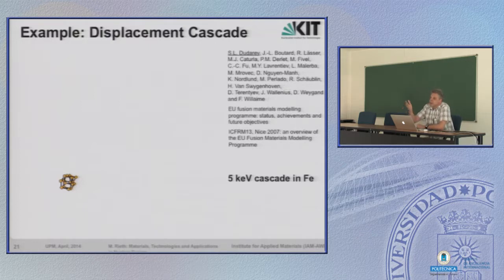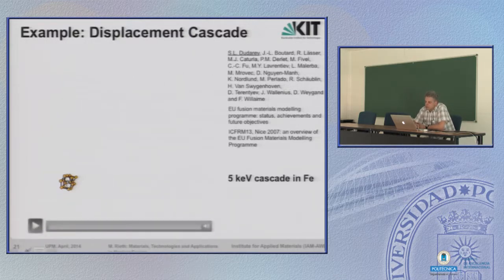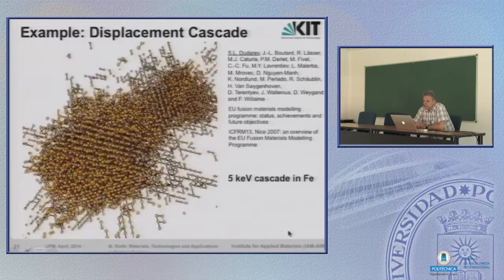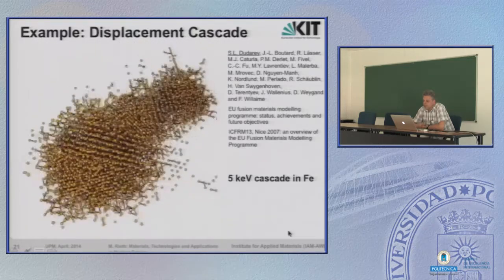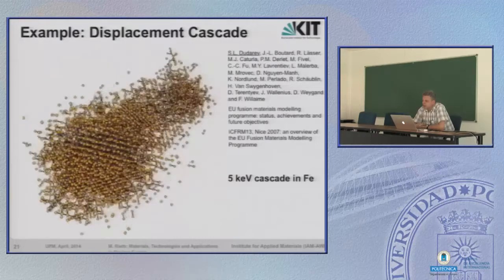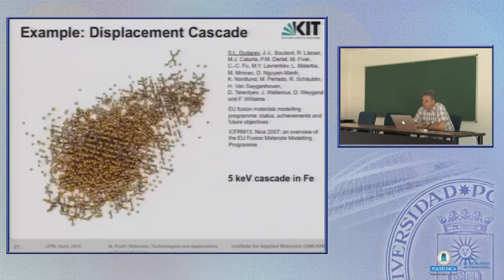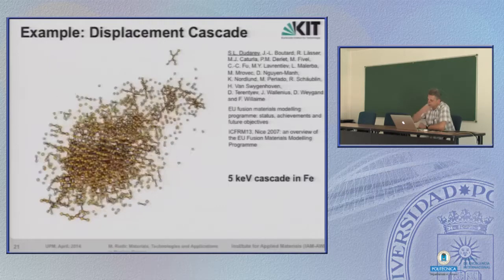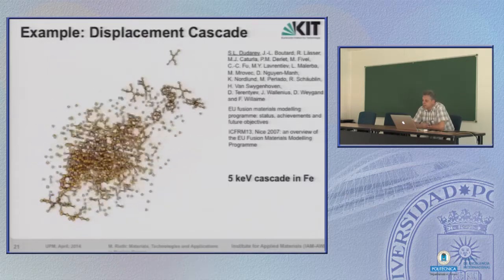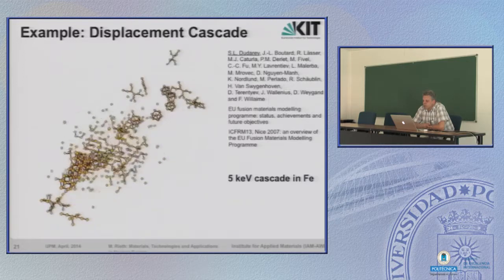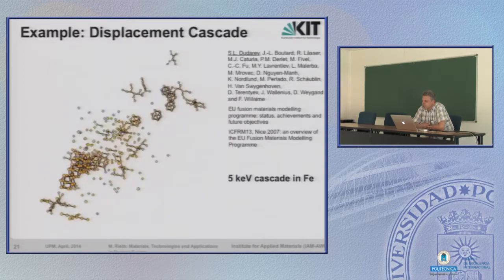Just an example here, again, molecular dynamics is a suitable instrument to simulate this. Here we have an incident particle of 5 kilo electron volts, which collides with an iron lattice. And this is how such a cascade develops. You see a big number of Frenkel pairs, that's only the atoms which are displaced from their lattice sites. And over time, the number goes back again, it's reduced.